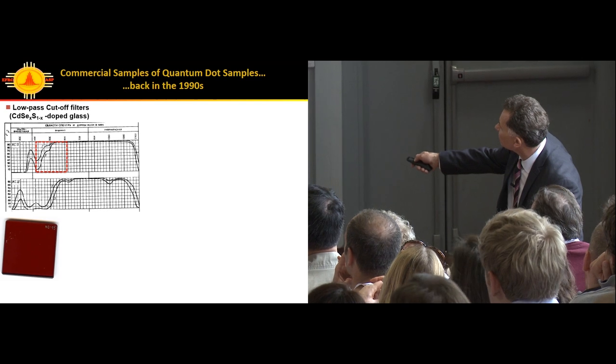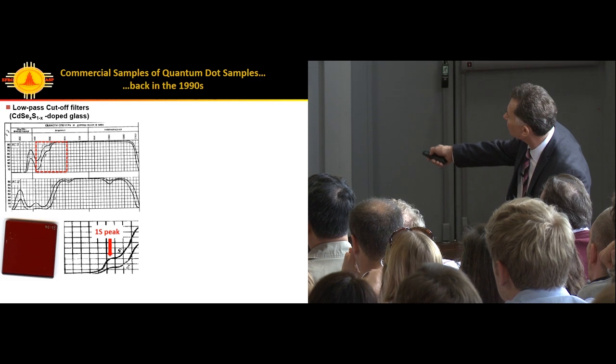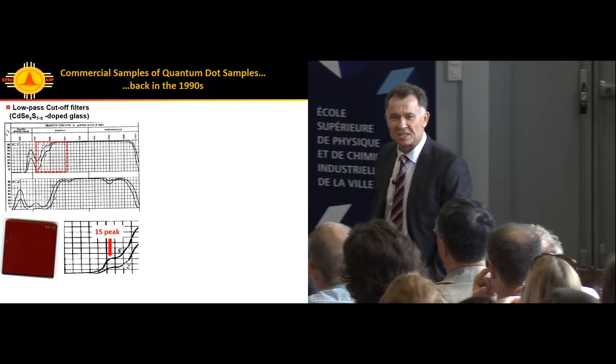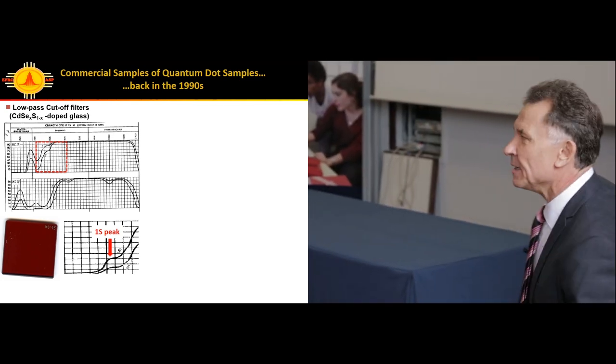We use them for meaningful studies. First, are they actually quantum dots? This is bandgap transmission. Let's do a bit of massaging, PowerPoint massaging. We check this region and rotate by 180 degrees. Now you recognize this is a well-familiar 1S-1P feature. So we are looking at quantum dots.